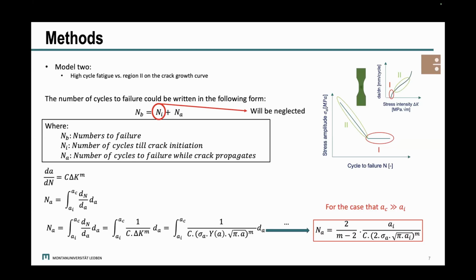In the second approach, they try to find the correlation between the second regime on the crack kinetic curve, and also between the high cycle fatigue regime on the SN curves. As I mentioned also in the introduction, we can divide the lifetime of the component into two parts: crack initiation and crack propagation. But considering that from the beginning we have a defect in the component, we can neglect the crack initiation part and consider that in the whole lifetime of the component, we have crack propagation.